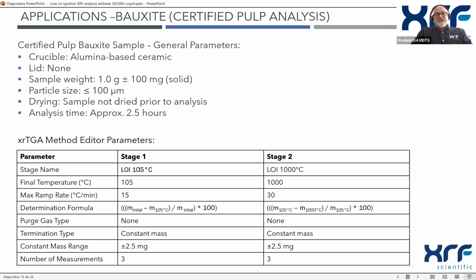The first stage is for the moisture determination at 105 degrees. For that, we have a heating rate of 15 degrees per minute. And we will check the mass constancy 3 times. We need to have a constant mass in the range of plus or minus 2.5 milligrams.